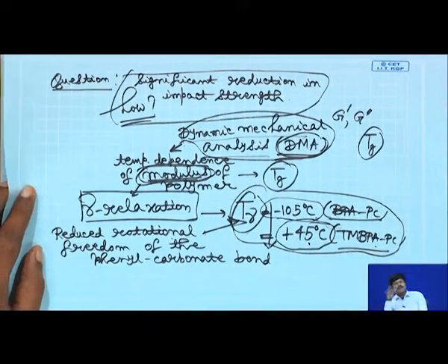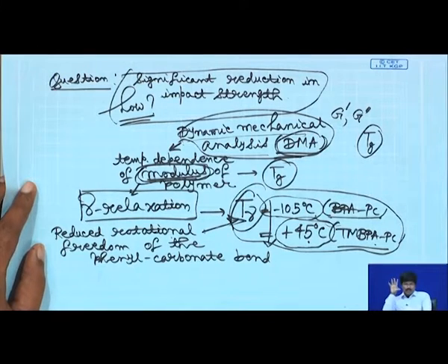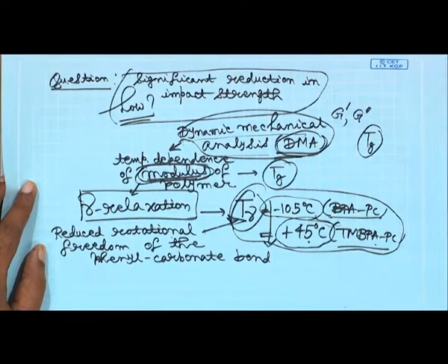Somewhat intuitively you can understand that when you give an impact to the material, it has to absorb some energy and yet it has to distribute that absorbed energy in the material. This possibly happens because you put in some energy and there might be slight rotation here or there of the bond, and you can absorb some energy. If you stop that, you cannot absorb and distribute this energy. So, it is an intuitive way to correlate the relaxation.